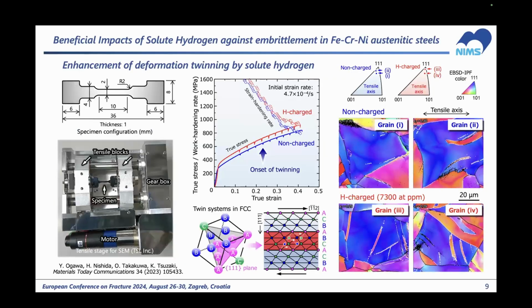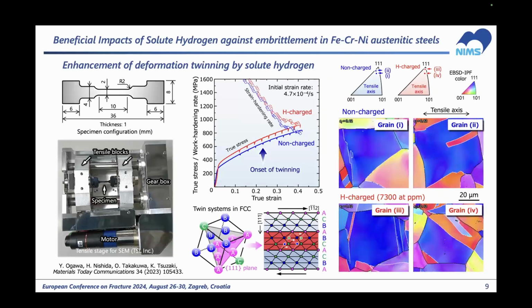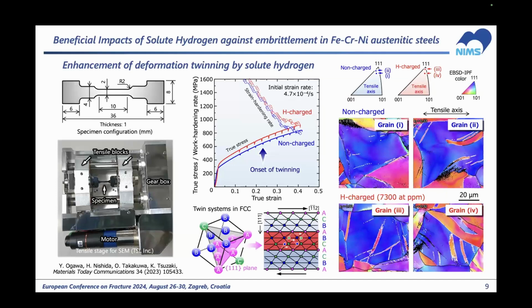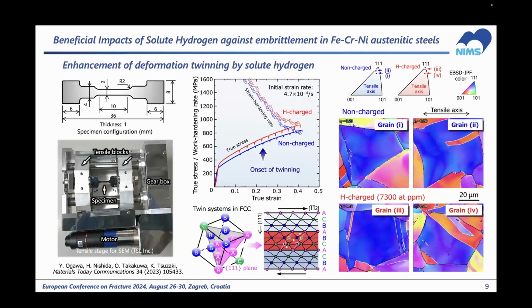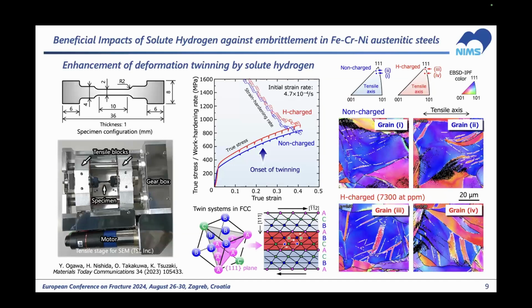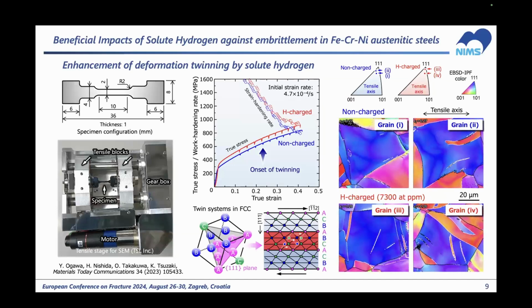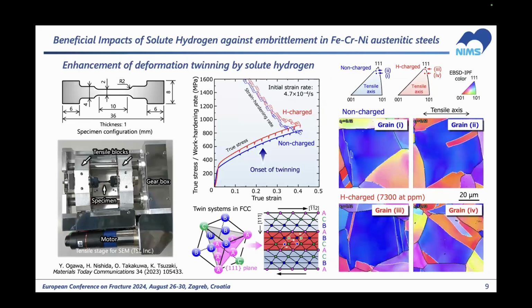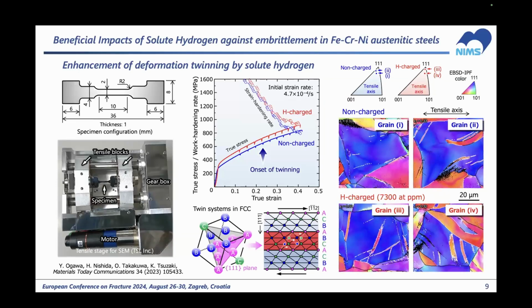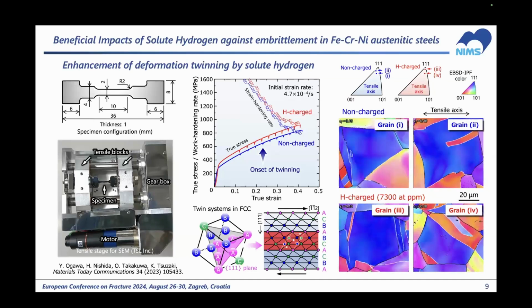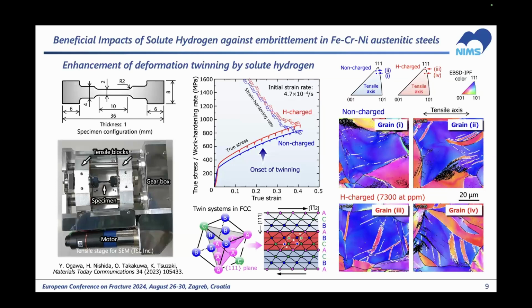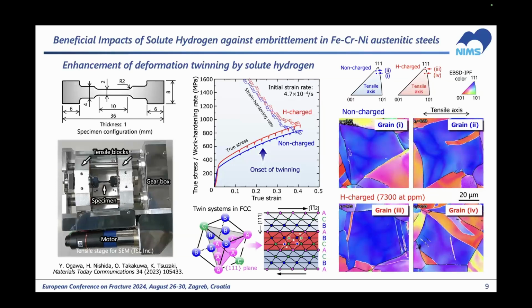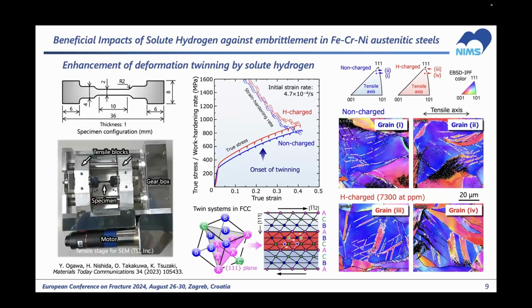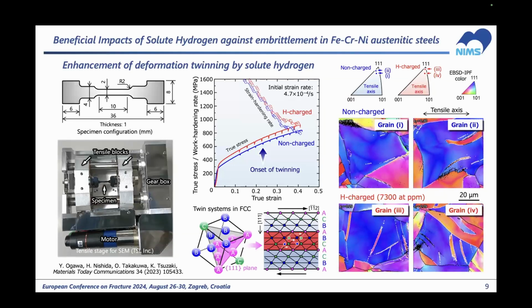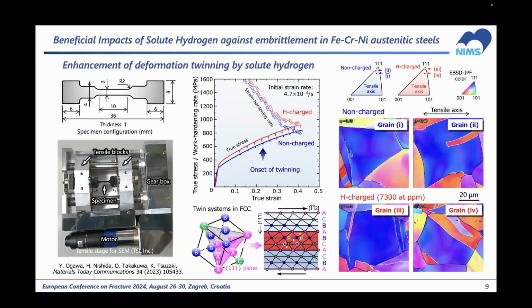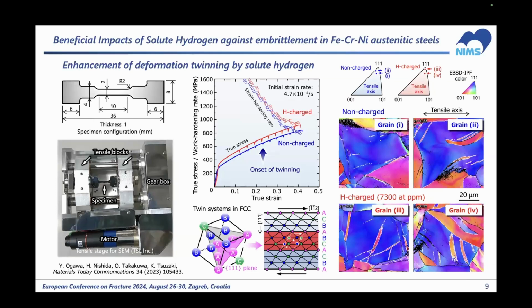And we also analyzed how hydrogen affected the deformation twinning behaviors by conducting in situ tensile straining experiments in SEM. We found hydrogen not simply densified the deformation twinning, but also accelerated the activity of secondary twins in addition to the primary twins, which were non-parallel to each other. So the emergence of secondary twinning made the dislocation blocking effect more significant. So it enhanced the work hardening rate at the latest deformation stage, and then resulted in the improvement in the uniform elongation.